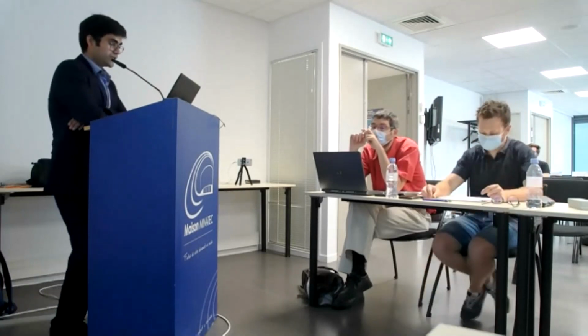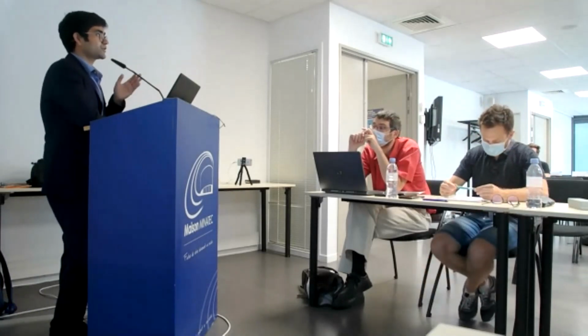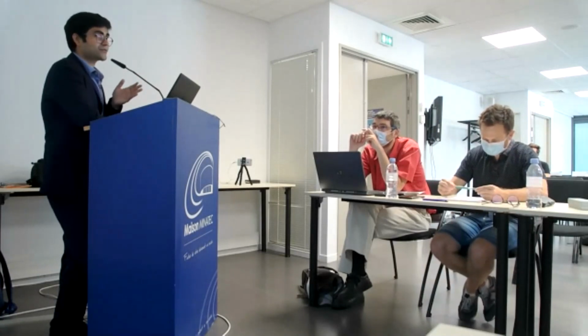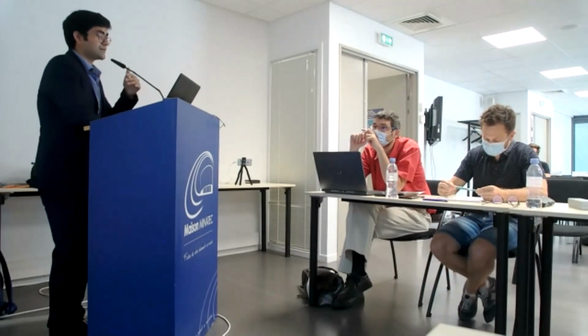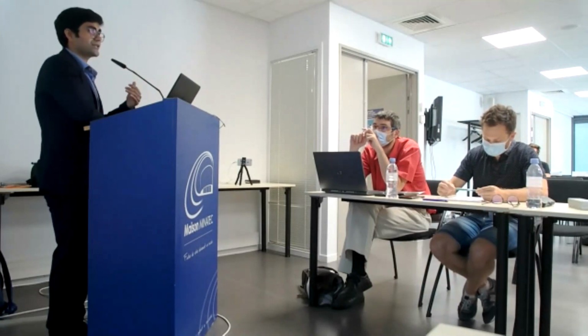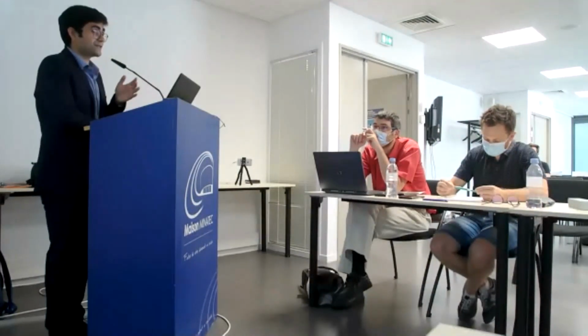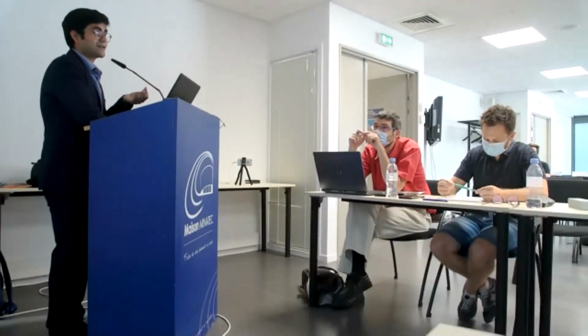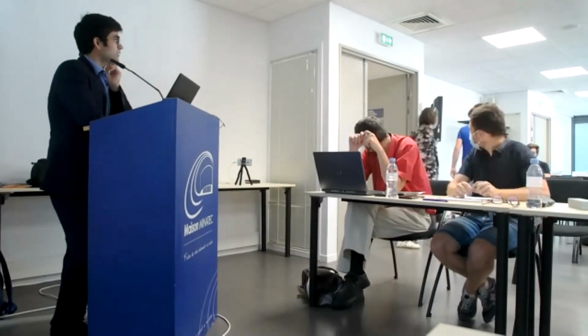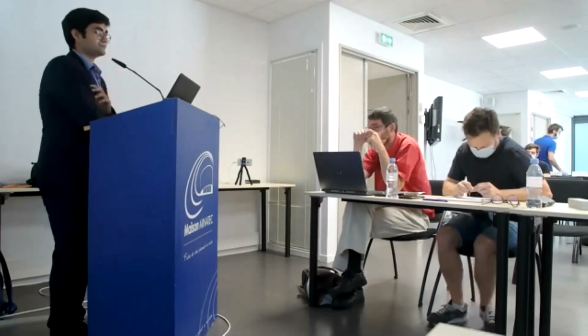But we also need to study the kinetics of this precipitation, for example, at what time they are forming, whether the precipitates have already formed before the cracking, or after the cracking, when these precipitates are really taken into account. So I think the kinetics of this precipitation needs to be studied in detail. We haven't done this in our study, but it might need attention in order to understand the interaction in a proper way, I guess.